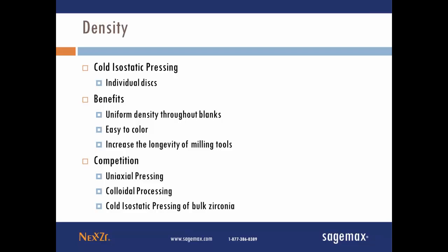The colloidal processing method is basically adding chemicals to a batch of powdered zirconia and letting it coagulate, and then it's pressed and cut and then sent to the labs and the milling centers. This is not a very good way of processing zirconia. There are very, very unique drawbacks to using these types of processing methods because you are not going to be able to color it very well, because of the non-uniform density in the blank.